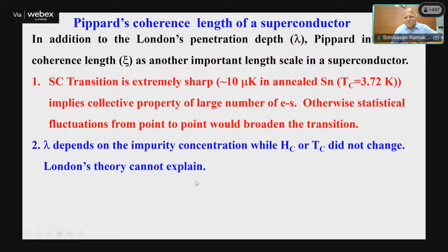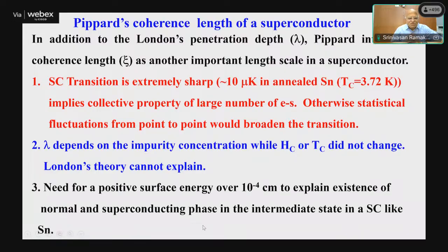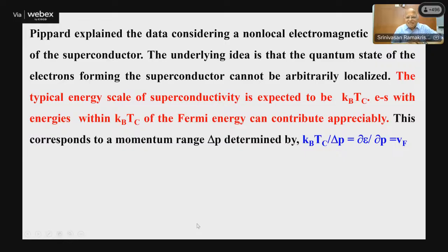And lambda depends on the impurity concentration, while TC and critical field don't change. So London theory cannot explain this. Moreover, we need a positive surface energy of the order of 10 to the power minus 4 centimeter to explain the existence of normal and superconducting phase in the intermediate states of superconductor. You could also get an intermediate state in a superconductor, and for that you need a positive surface energy, which London theory couldn't give. So he said the electromagnetic response is non-local, not like a local expression which London gave.